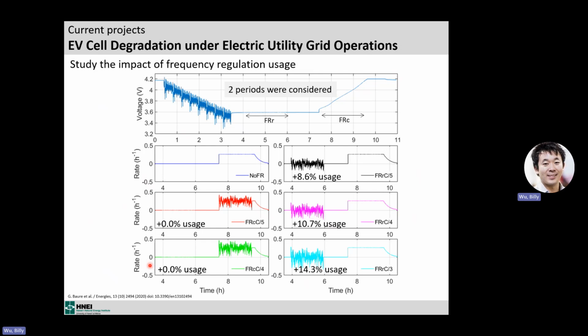So then we had the idea of what if we modulate the charge? What if we, instead of charging at constant power, which was pulses, always charge, but with different amplitude for the charge. That way we can test without actually inducing any additional usage on the cell. And what we found with our study is actually when we did that, we had zero impact of frequency regulation on the degradation.